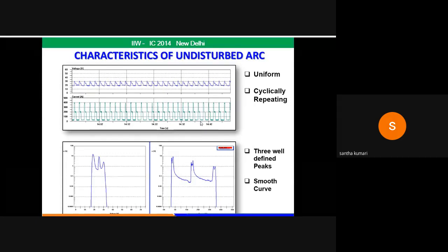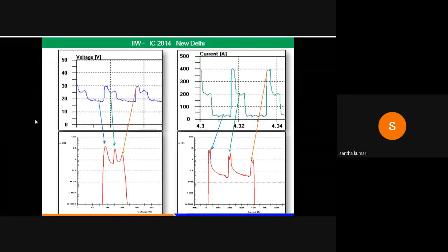In the PDD also, we can see three well-defined peaks with a smooth curve for a good weld. The current and voltage are recorded with respect to time in seconds. These values are cyclically repeated for undisturbed arcs. These regions are reflected as three peaks in the PDDs, both current and voltage, corresponding to the three regions of the distribution of the values.